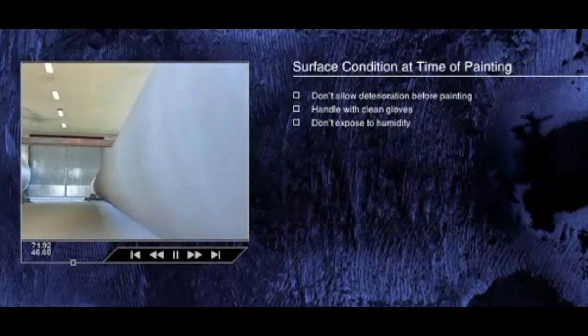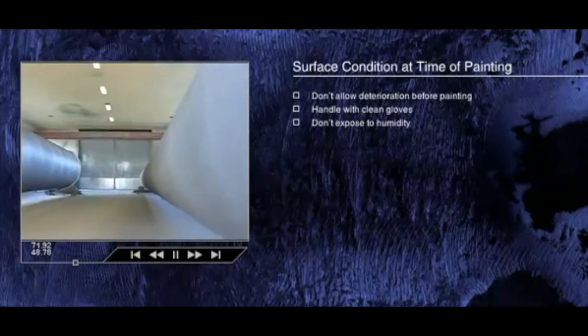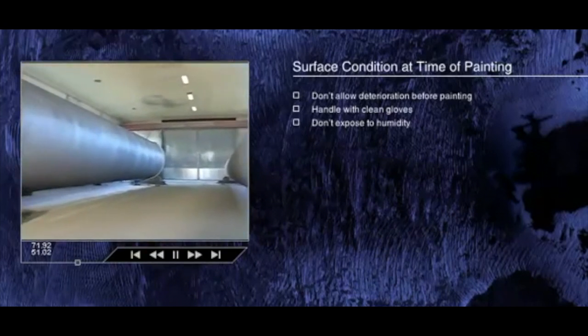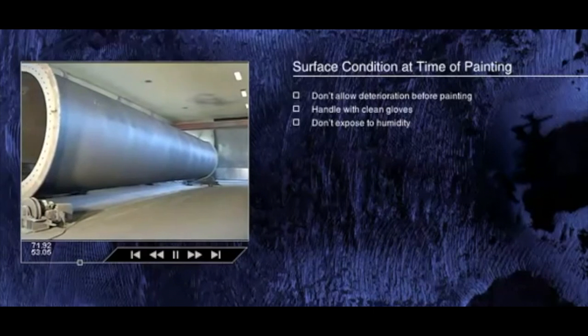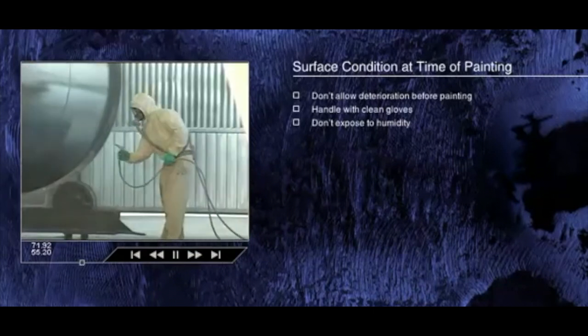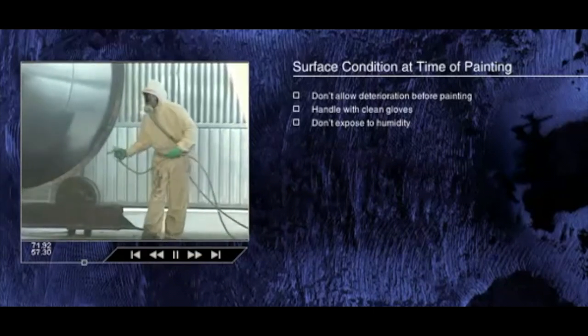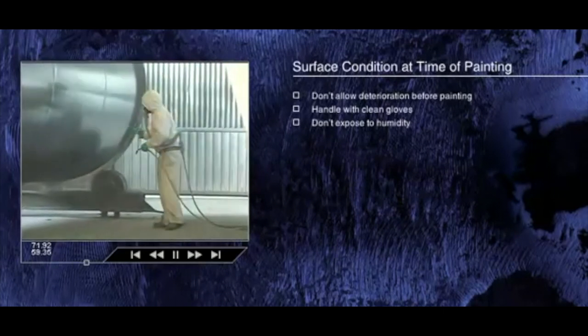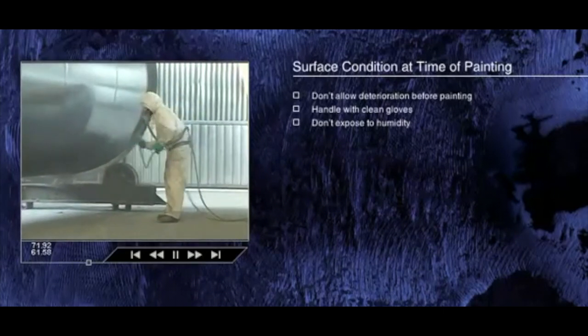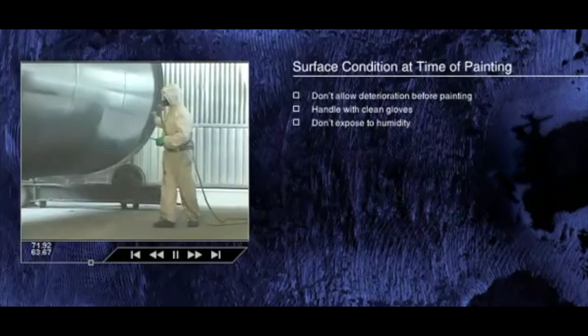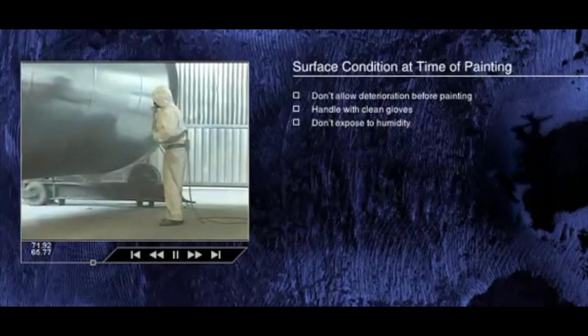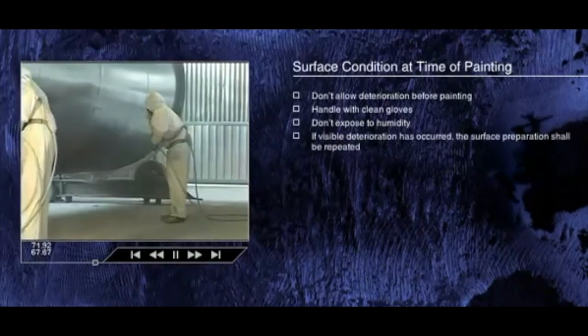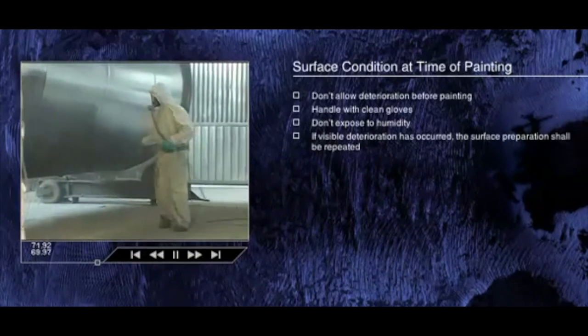As far as practicable, any storage after blast cleaning should be in a warm, dry environment, and ideally, spraying should follow blasting as quickly as possible. Commonly applied rules indicate a maximum delay of 4 hours and require that if visible deterioration has occurred, the surface preparation shall be repeated.